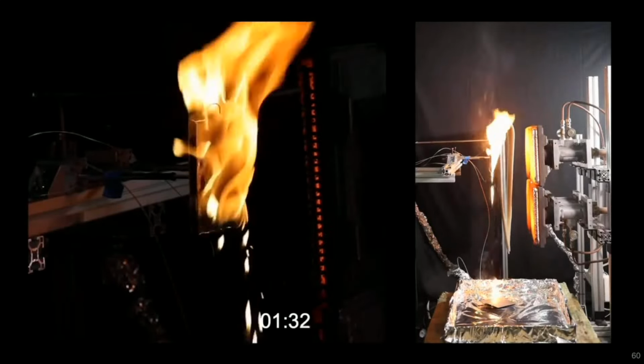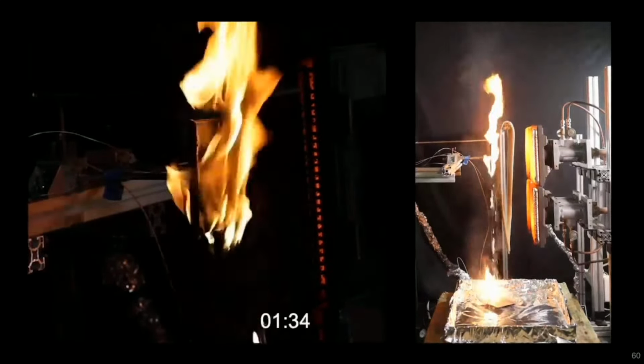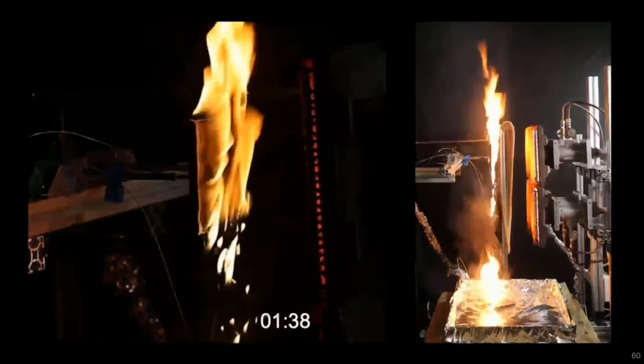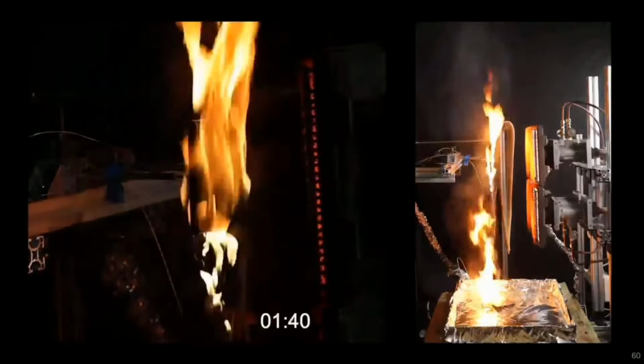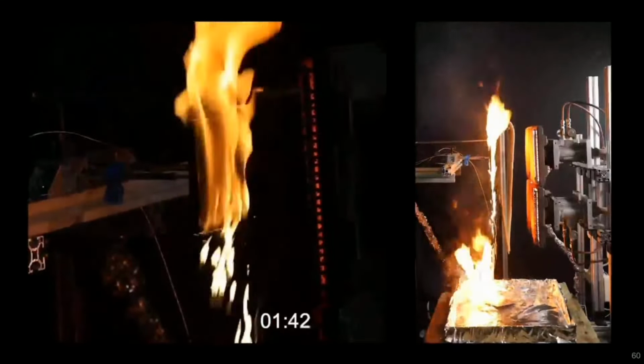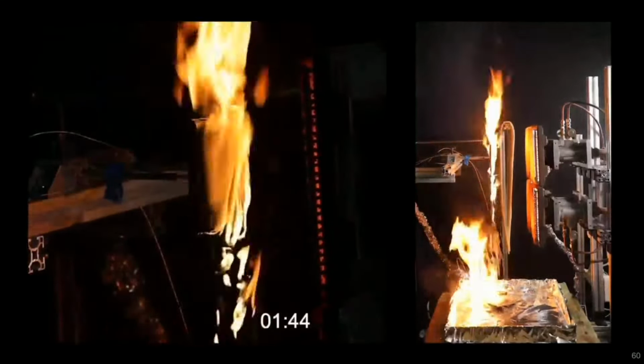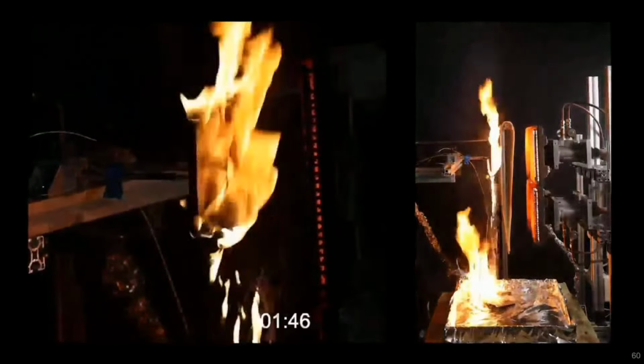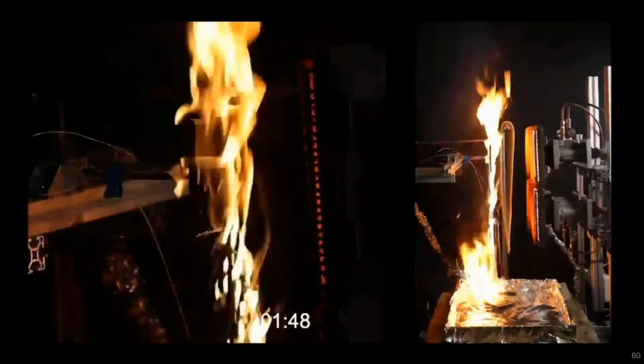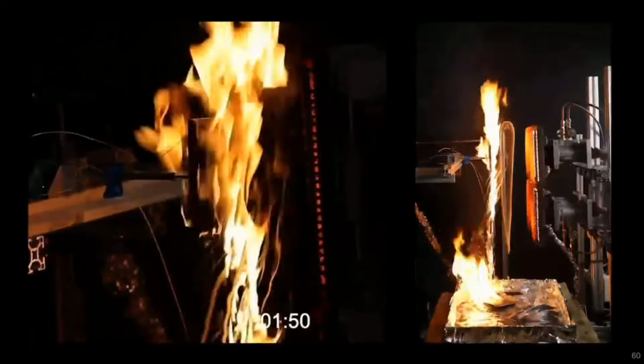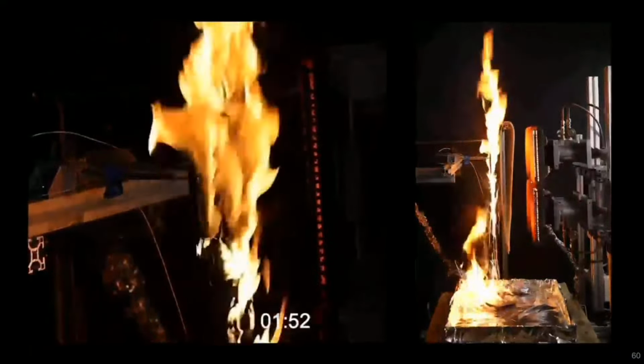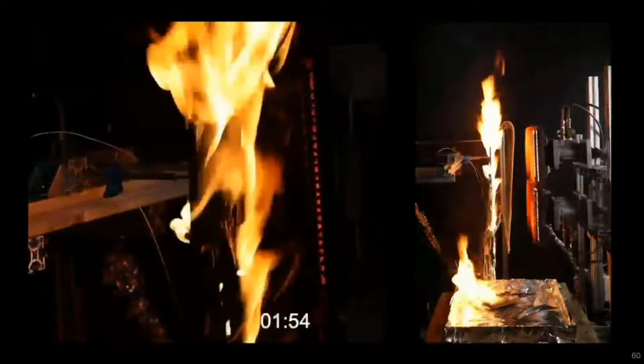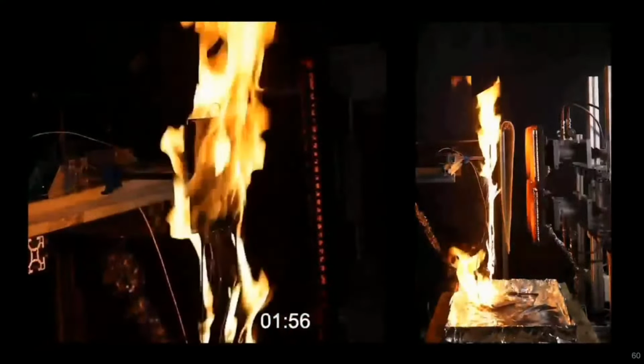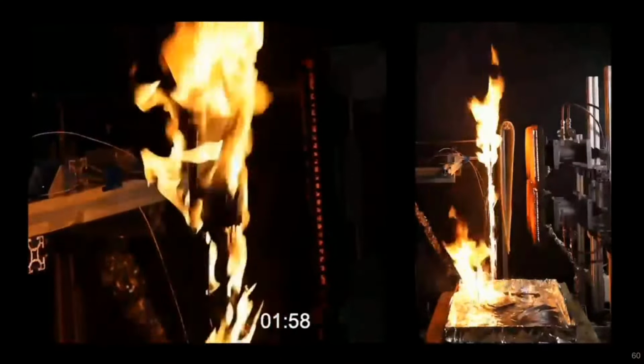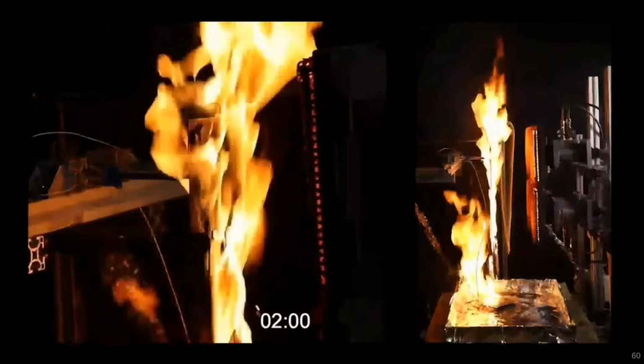The rate of droplet production increases quite rapidly, and a continuous stream of burning polyethylene falls into the debris tray and increases the size of the pool fire. It's probably also worth having a look at the left-hand image, just the way the polyethylene is melting and flowing and dripping, which you can sort of make out through the flames.